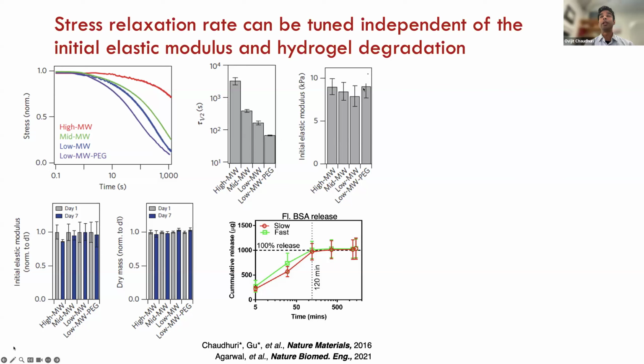Now, importantly, we can vary these properties independent of the initial elastic modulus, or that initial resistance a cell feels as it first pushes or pulls on these hydrogels. So that's shown here. The modulus in these gels is around 10 kilopascals. We can use other formulations and vary the modulus from hundreds of pascals to about 20 kilopascals, while having a range of viscoelasticity that we can access.